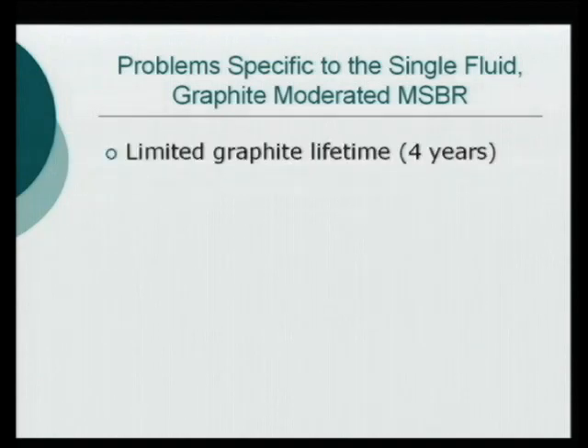Now, some problems specific to the molten salt, the single fluid, where you mix the thorium and uranium in the same fluid, graphite moderated design. They had a fairly high power density, and graphite has a limited lifetime depending on your power density. So it has a lifetime of 4 years. We have to replace that graphite every 4 years.